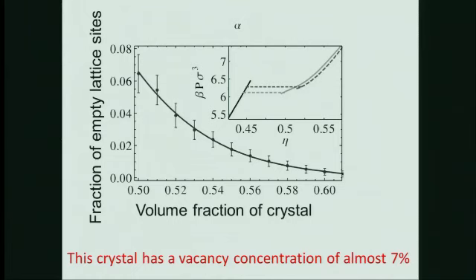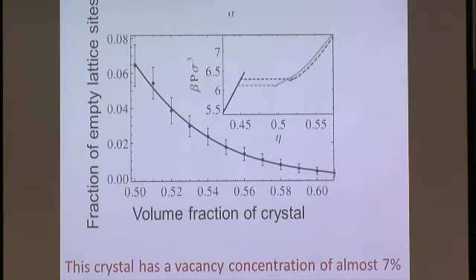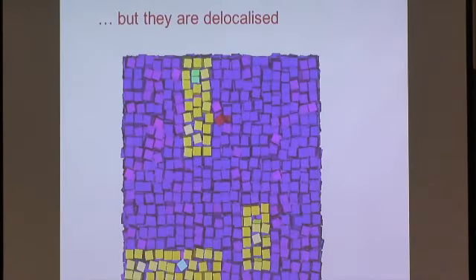In mixed systems, yes, if you go to superionic conductors or whatever, there are all kinds of examples. But for pure systems, there's nothing like this at all. And it makes a difference for the phase diagram, but I'll not go into that. As you go to high density, you squeeze out the vacancies. Now this is a snapshot, and the snapshot shows that you can't see the vacancies, because they're delocalized. And that tells you something about the mechanism.